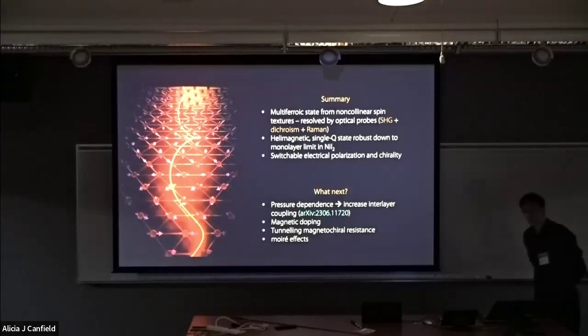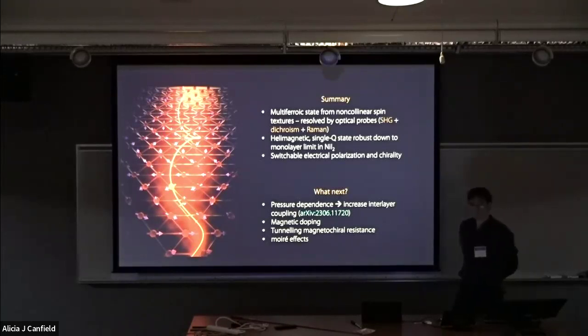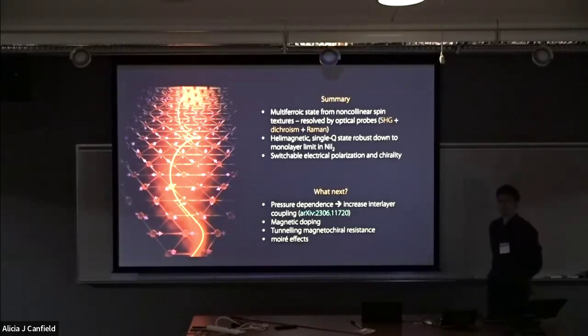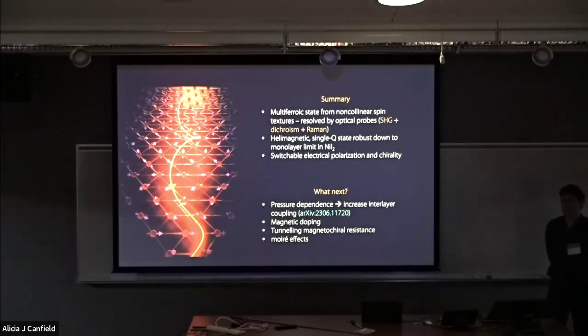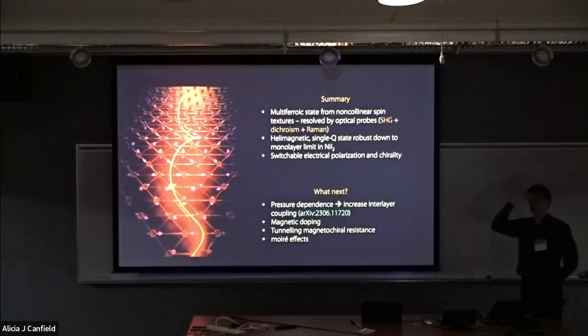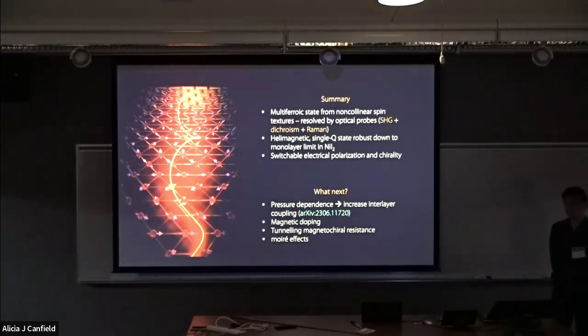There is a direct way to distinguish helical and cycloidal spirals. If you apply a field in the helical plane, you should observe a spin flop, and I would think that it shouldn't be prohibitively large. Did you try to find one? It actually turns out in this material to be pretty large. And maybe that's where, to my second point, when you are working with your minimal model, it may or may not be important, but I don't think that the minimal model should include single-ion anisotropy rather than anisotropic exchange, like isotropic type exchange.